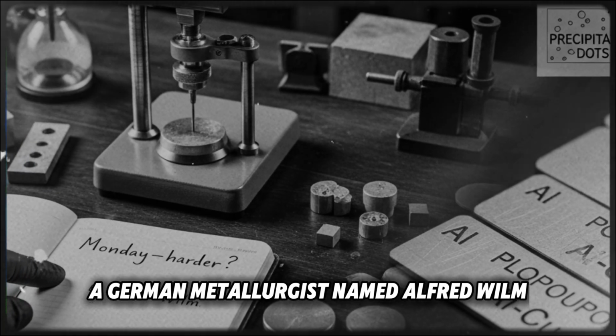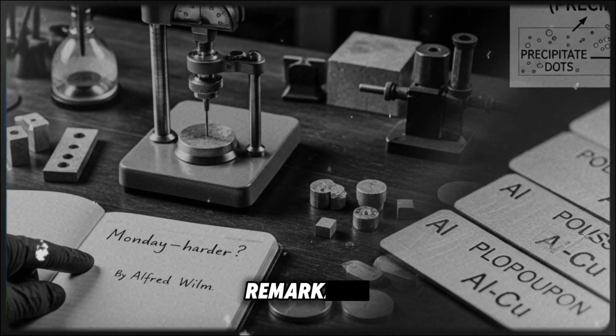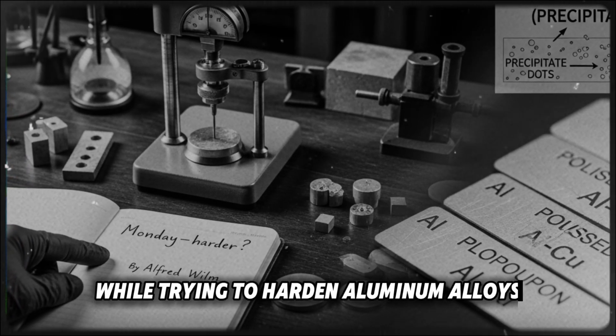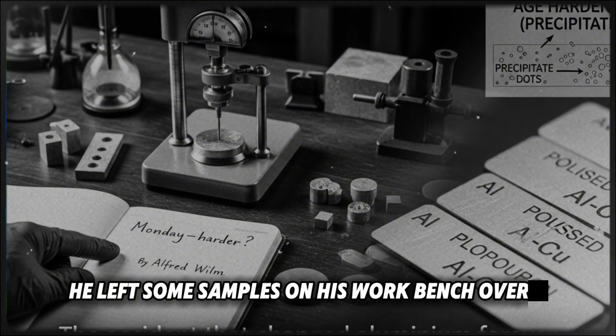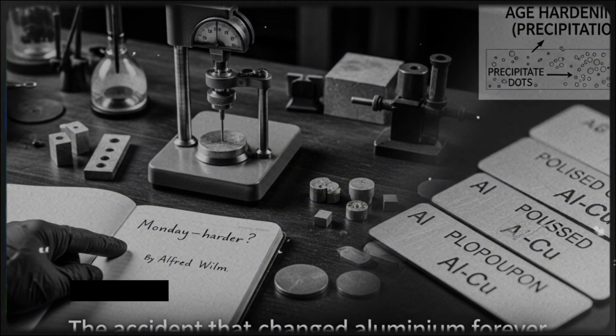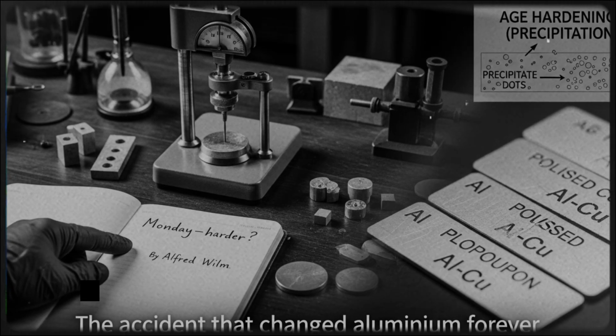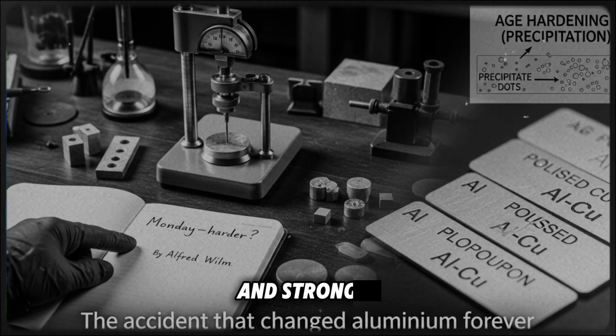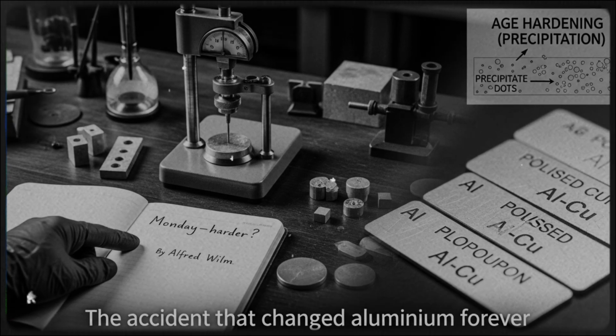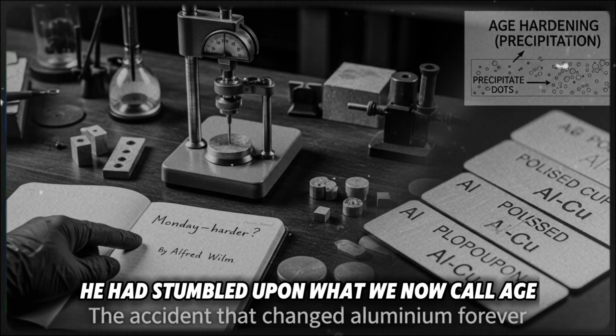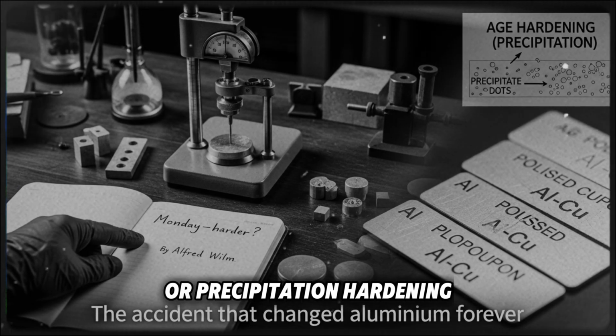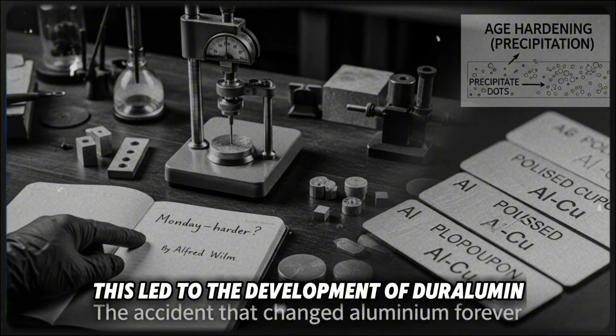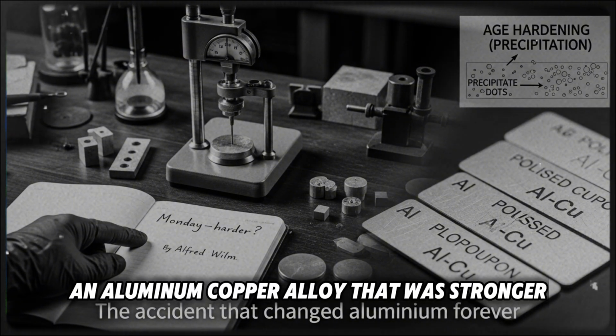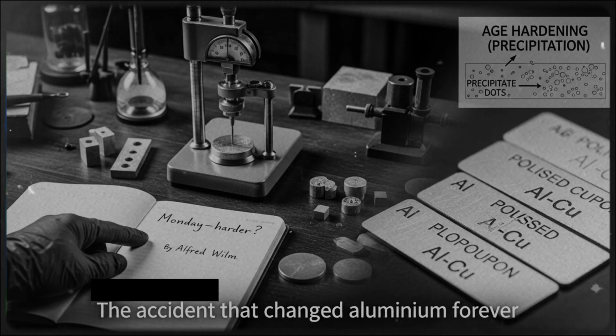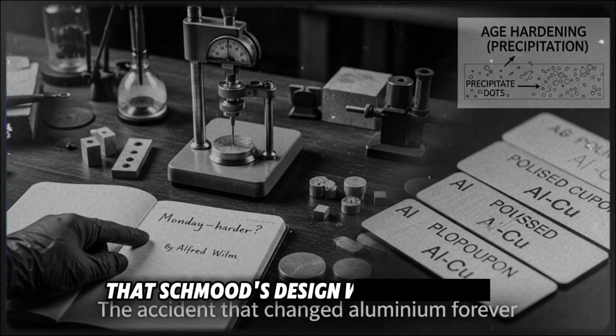In 1906, a German metallurgist named Alfred Wilm had accidentally discovered something remarkable. While trying to harden aluminum alloys, he left some samples on his workbench over a weekend. When he returned and tested them on Monday, they had mysteriously become much harder and stronger without any additional treatment. He had stumbled upon what we now call age hardening or precipitation hardening. This led to the development of duralumin, an aluminum-copper alloy that was stronger than pure aluminum. But it still wasn't strong enough for the stresses that Schmued's design would generate.